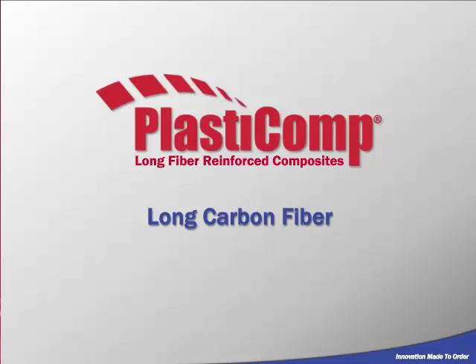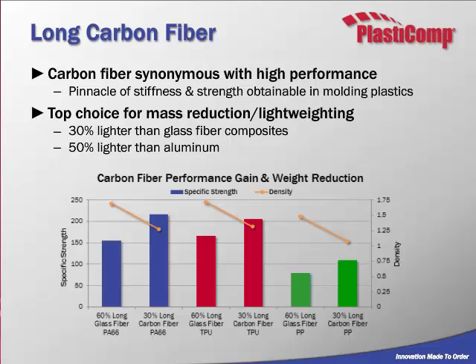So now we're going to just touch on long carbon fiber. And I think the first thing that comes to mind when we mention carbon fiber or carbon fiber composites is performance. Everybody thinks about that you've got very high performance with carbon-filled materials. And when performance is of the utmost importance, carbon fiber will win out hands down. The density compared to glass is lower. And when you use a carbon fiber reinforced material, you can get a product, when designed properly, that's 50% lighter than an aluminum part.